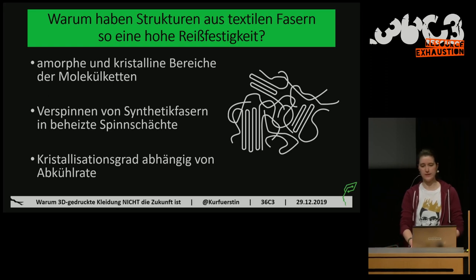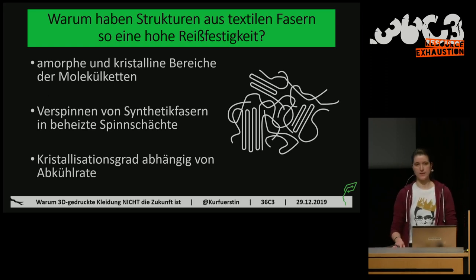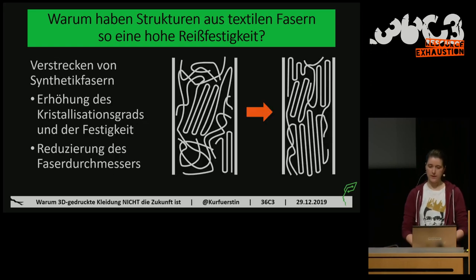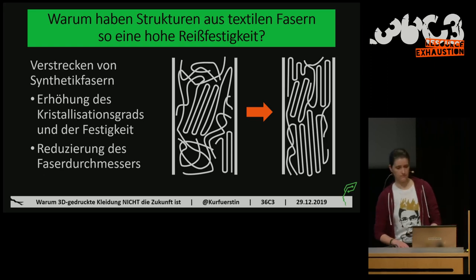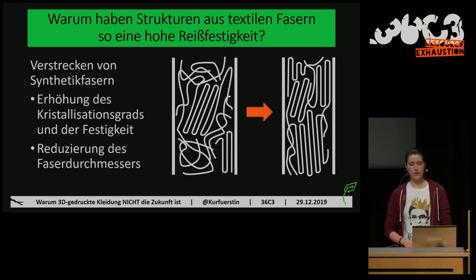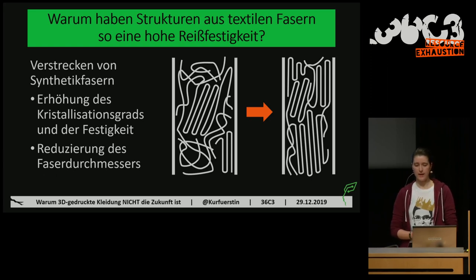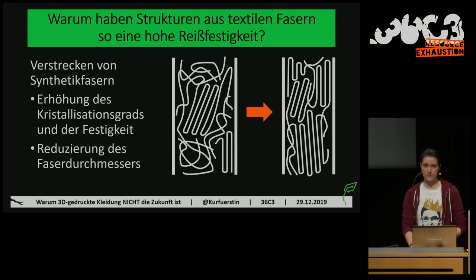It's better for making high tensile strength materials, and the structures had significantly better results as far as tensile strength goes. With synthetic fiber, we have another possibility, which is stretching them. After they've been spun, they are shoved through rollers, and these rollers pull on them and apply a pulling force, and that raises the degree of crystallization because the molecules are forced to align to each other. This also leads to the fiber becoming slightly thinner, and it becomes finer, softer, but more solid.